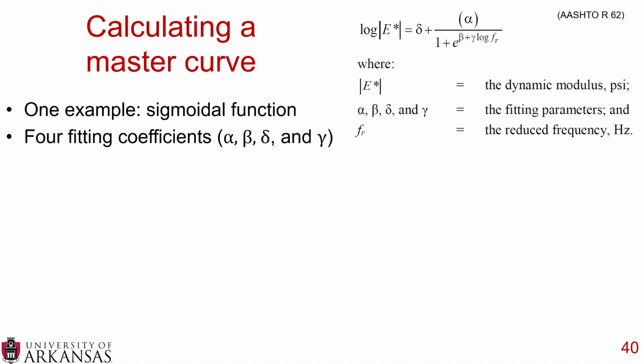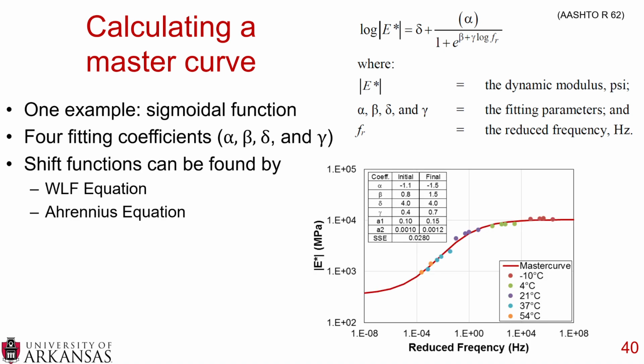But it's important to note that you have 4 fitting coefficients, and so what you need to do is you need to shift the data, and you can do that either by WLF or the Arrhenius or other various methods. But you can see here the original data, the -10 is on the far right, the +54 is on the far left, and we shifted that data to various reduced frequencies, and then we put a fitting parameter to it. And that's that solid red line, which is the master curve. And you can see the various coefficient values and the standard square error. So you want to minimize that. We usually use Microsoft Excel Solver to minimize that, but it's a very powerful tool in asphalt materials.